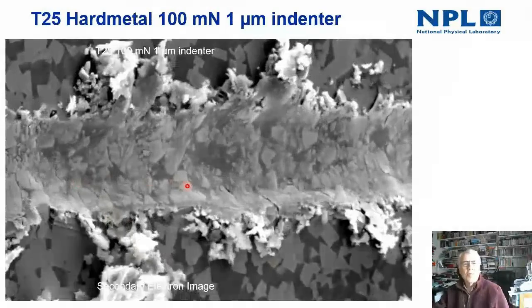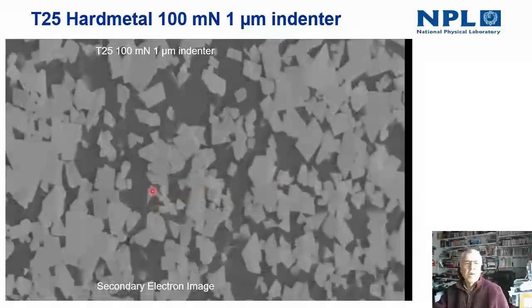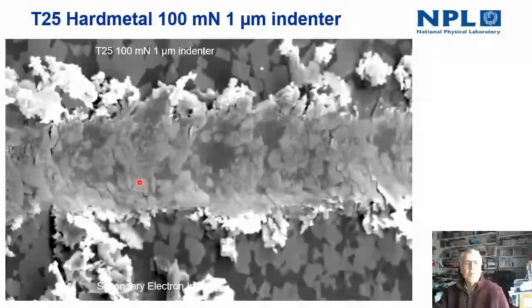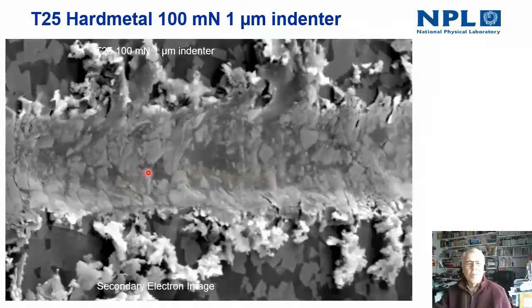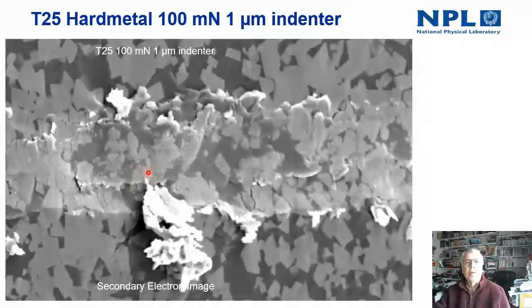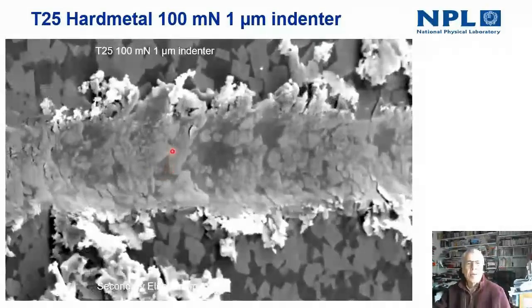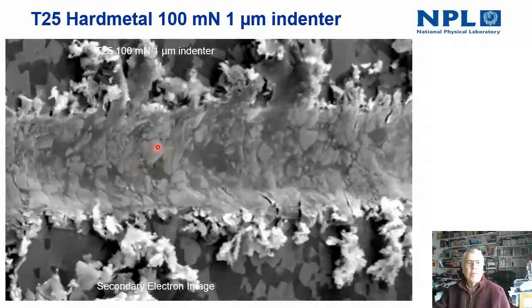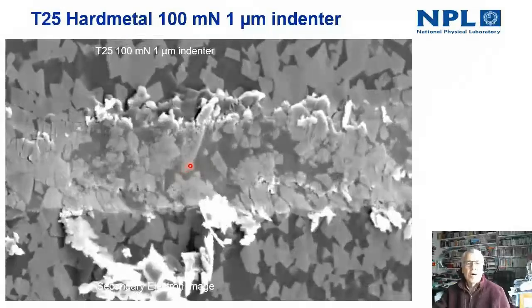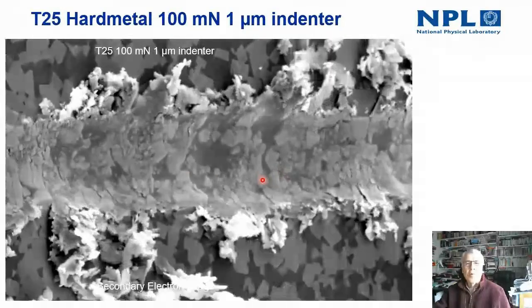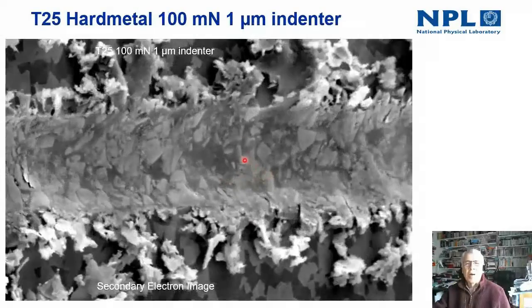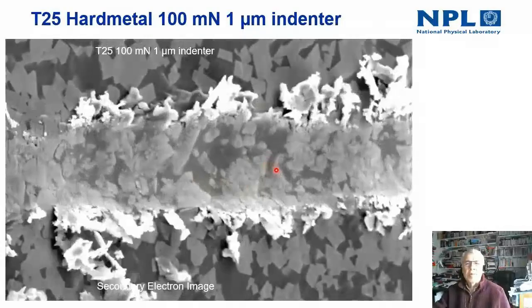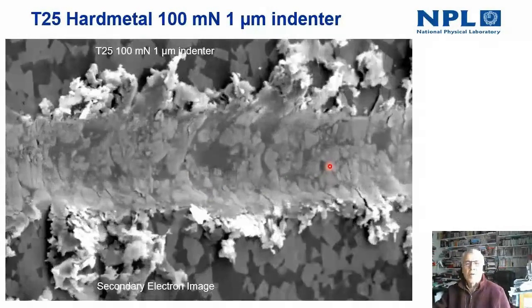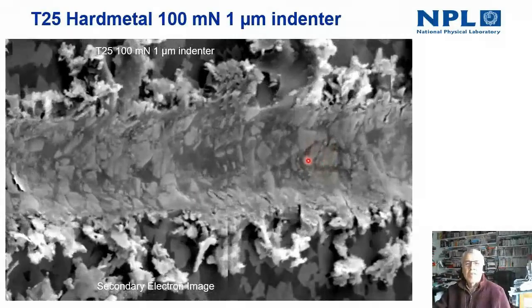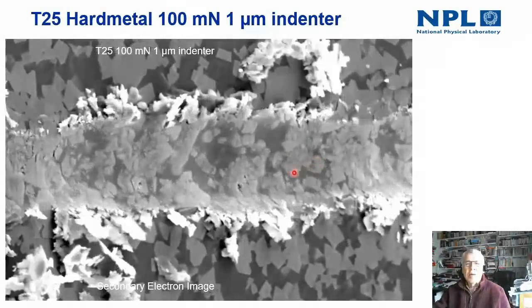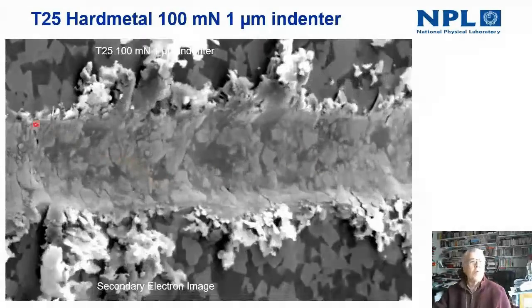And the beauty of this sort of analysis is you can see the detail of how the material behaves under the effect of the mechanical overstressing from, in this case, the diamond indenter. And you can see here that grains of material are fragmenting, they are embedded into the surface of the cobalt, they then flow out from that and into the surface. So for example, look at this grain of tungsten carbide here, which gradually fragments and is reduced to rubble almost.